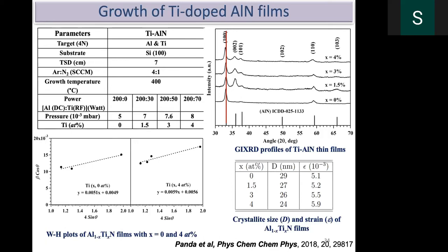Basically, just now I have shown that when you increase the titanium, the hardness should increase. But that is at a very large level of titanium. That means aluminum is a very small quantity, roughly 18 or 20 atomic percent. But in this case, aluminum nitride is predominant, so titanium is a very small quantity. So hardness comes mainly because of the microstructure, and we wanted to see how much this titanium replaces the aluminum.